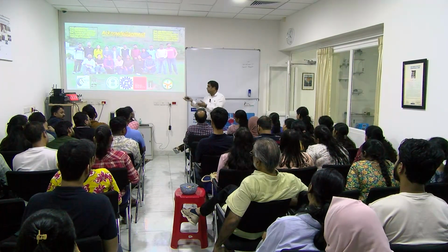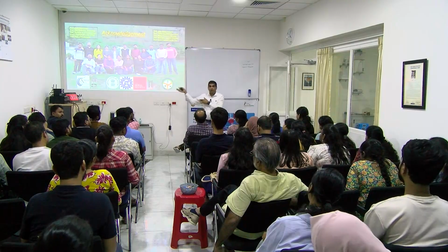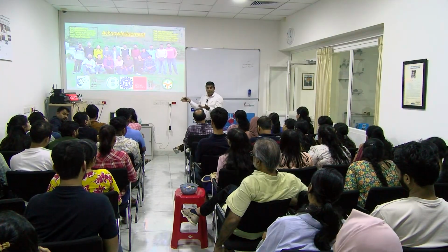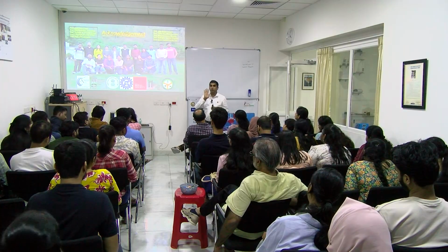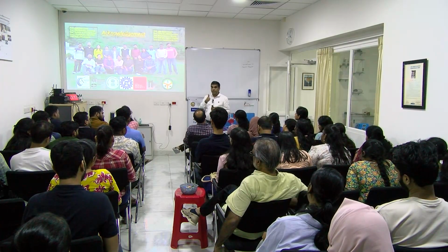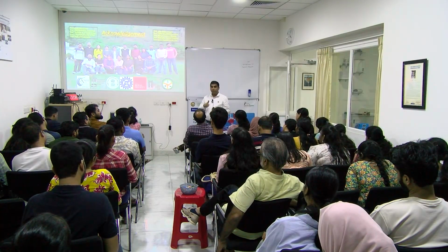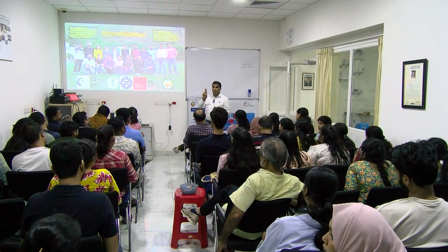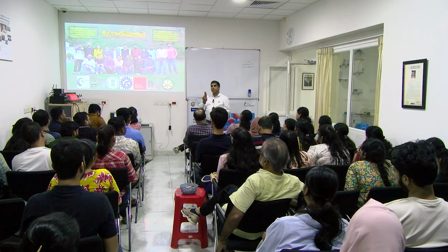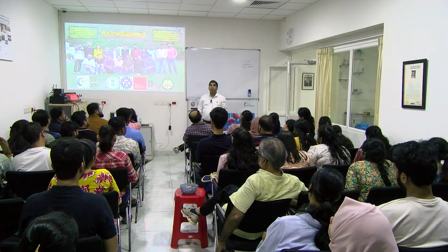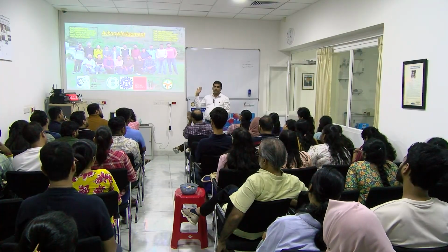So it depends; it is not universal. I have shown that it is working as a single photon emission, but it is still not ready for device fabrication, because there are other parameters. There are at least 5 parameters one has to work on for single photon emission. One is obviously brightness, the first and foremost important, the photon counts. At the same time it has to have a small lifetime as well as a very small bandwidth. If you have a large bandwidth, it has homogeneous broadening, which will contribute to impurity of the single photon emission. So there are several parameters and aspects we need to work on.